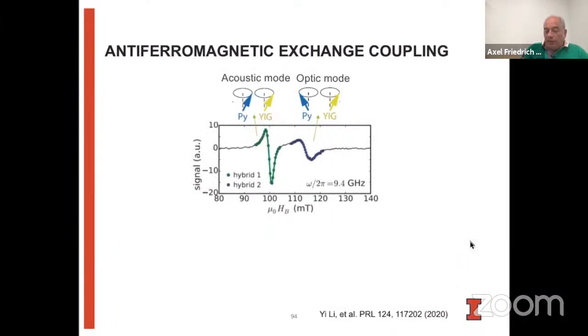So I should briefly also say that the fact that the acoustic mode is at a smaller resonance frequency versus the optic mode shows that we have antiferromagnetic coupling between the YIG and the permalloy, which is consistent with what has been observed before.